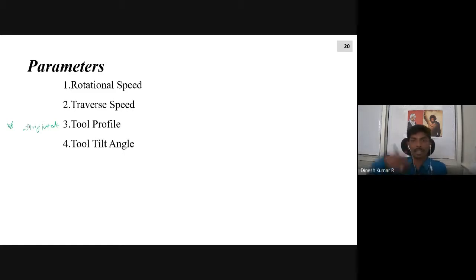What is the tool tilt angle? Whenever the process is moving on, there will be friction. When you have two components and the tool is completely at 0 degree, it makes a complete mating, which is going to have a lot of friction and is not going to be that effective. So the tool will be tilted at a particular angle. Say this is the tool at 0 degree, and we make that tool tilt around 1 or 2 degrees, so that the packing will be there. Still, the friction force will be eliminated because there is no friction happening throughout the process. It's like a board structure, an aerodynamic shape, where it slides at the front and compacts at the back. So we have one more parameter called tool tilt angle.